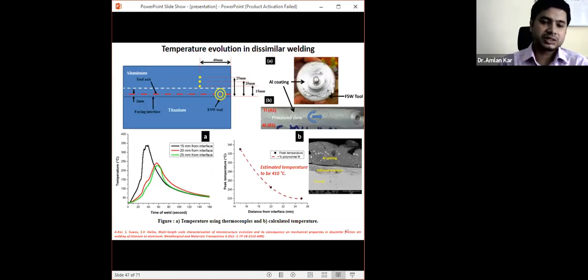So we have estimated the temperature, which is approximately 410 degrees centigrade. Because of this temperature, we can understand that at this temperature the aluminum behaves like a plastic material, but this temperature is very, very low for titanium. So this temperature is close to the melting point of the aluminum, unlike titanium. And so during the deformation, aluminum is subjected to hot deformation, but the titanium is subjected to cold deformation because of the difference in the physical properties. And due to that, the aluminum generally is recrystallized, unlike titanium, which is subjected to fragmentation.